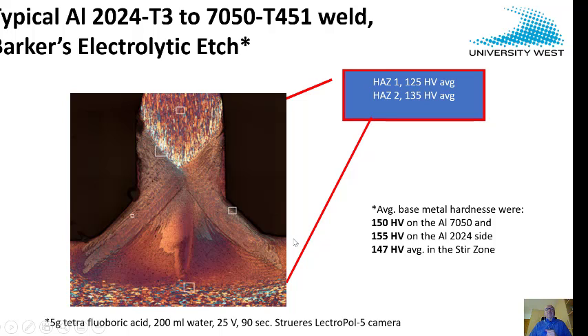For some reason my presentation locked. So here is the first cross section we did with, obviously we did Keller's etch. We did not get too much out of it. So we applied a fairly well-known etching technique called Barker's. It's an electrolytic etch which comes off with very spectacular results. You can see the composition here. Tetrafluoroboric acid at about 25 to 30 volts and for 90 seconds. And then you can use different filters to take very beautiful pictures of this.